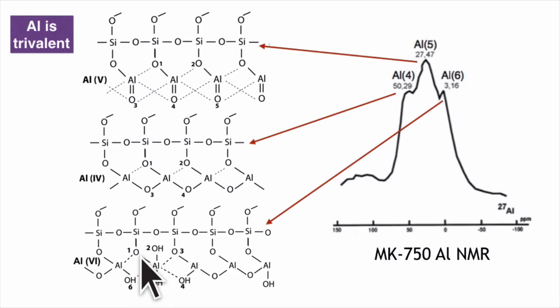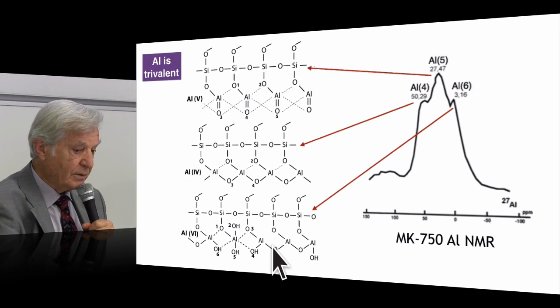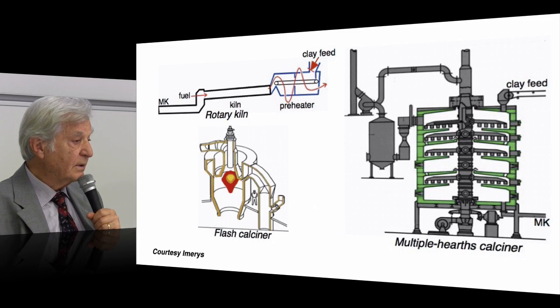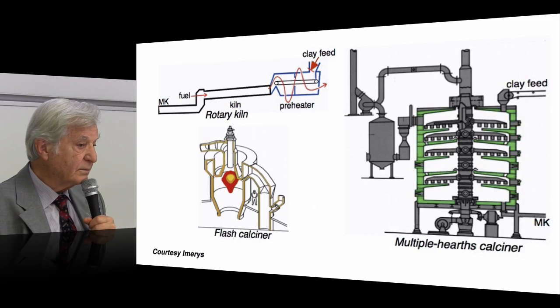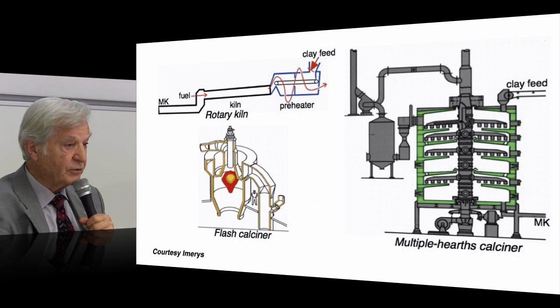It is surrounded by 1, 2, 3, 4, 5, 6. It is hexa-coordinated, but the aluminum is still trivalent, but has 2 OH groups. And these 2 OH groups behave differently than this oxide and differently than this one. It takes more time to interact to make a geopolymer. So we will have 3 steps. And depending on how it has been manufactured, you'll get more from one, less from the other, and this is what you have to know.